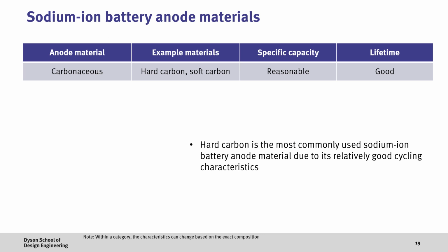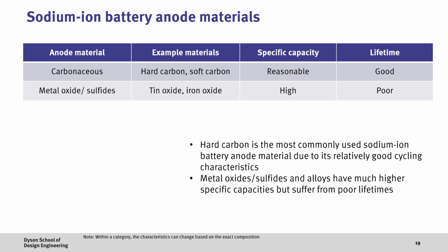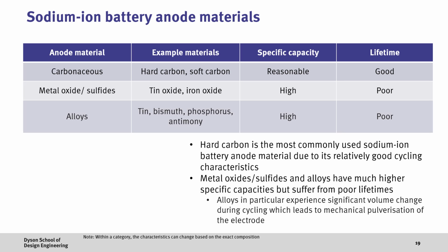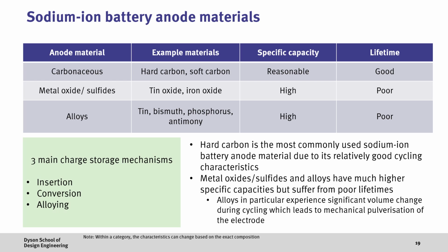Next, for anode materials, there are generally three main types. Carbonaceous materials, where hard carbon is perhaps the most popular. This has reasonable specific capacity and good lifetime. Metal oxides and sulfides generally have much higher specific capacities, but their lifetime can be poor. And similarly, alloying materials such as tin and phosphorus have again high specific capacities and poor lifetime, with alloying materials experiencing significant volume change during cycling, leading to mechanical pulverisation of the electrode and poor lifetime. Here, there are three main ways sodium is stored in the electrode: insertion, conversion, and alloying.